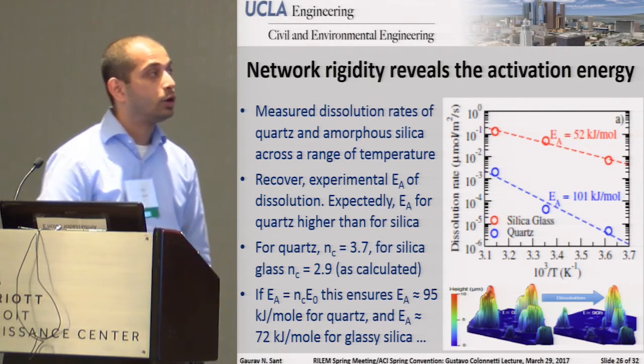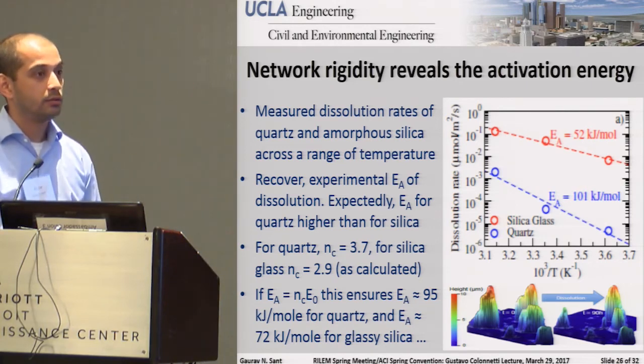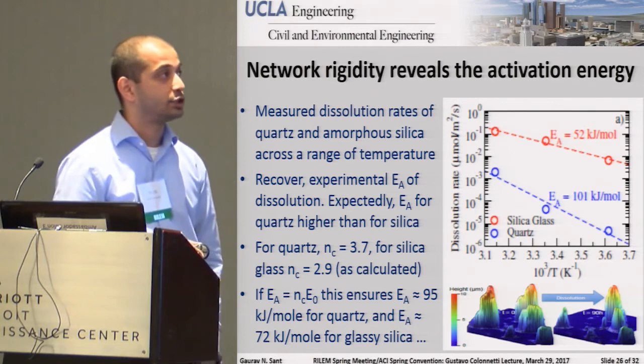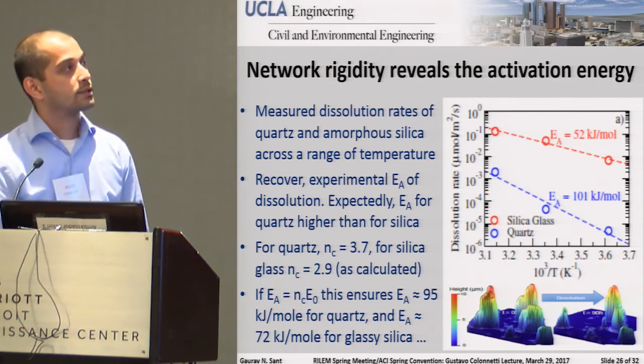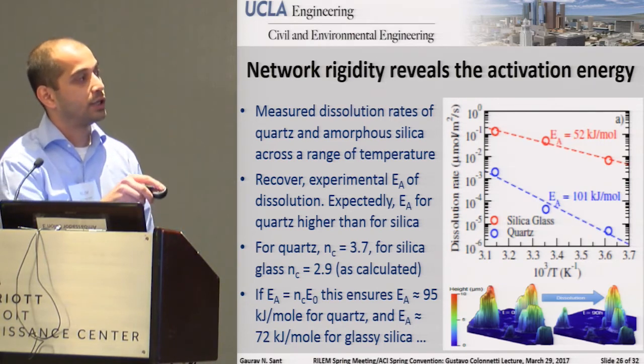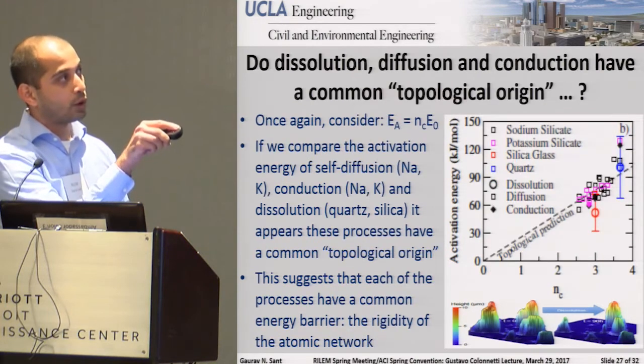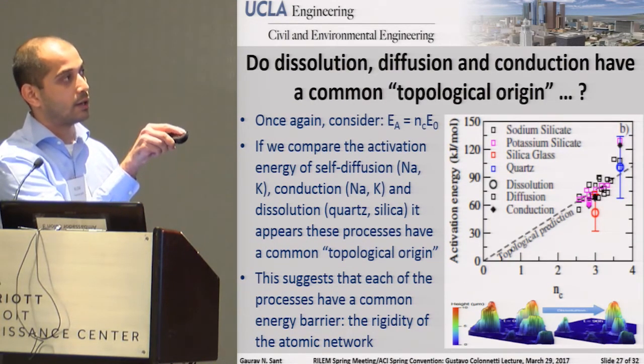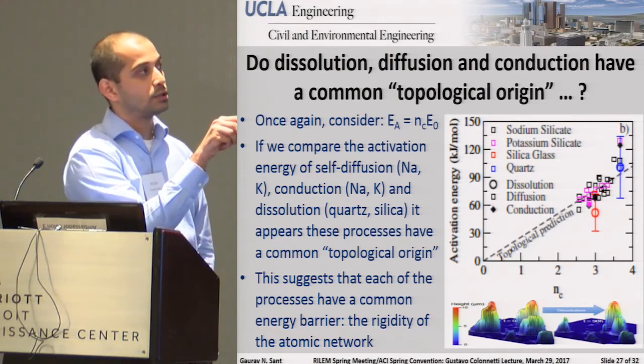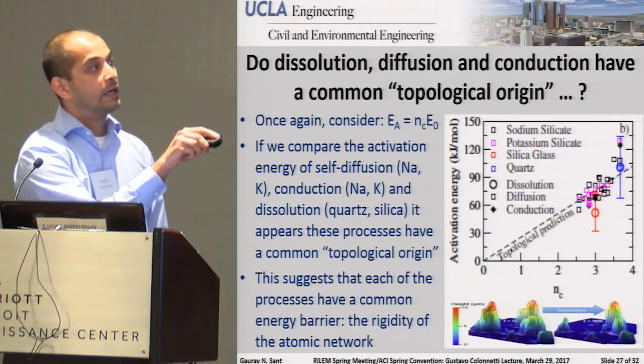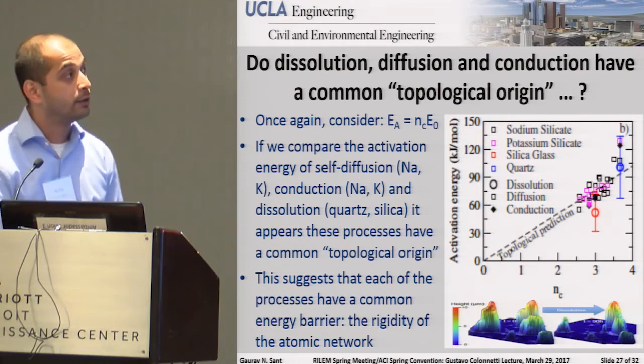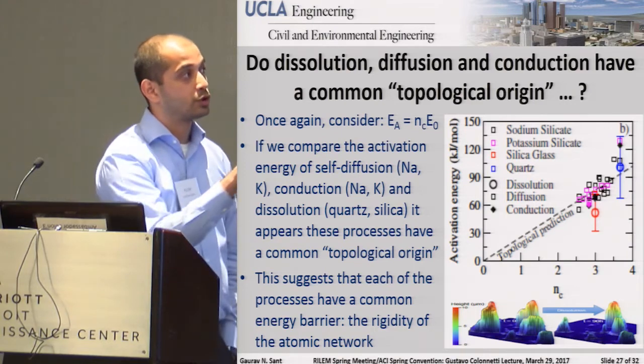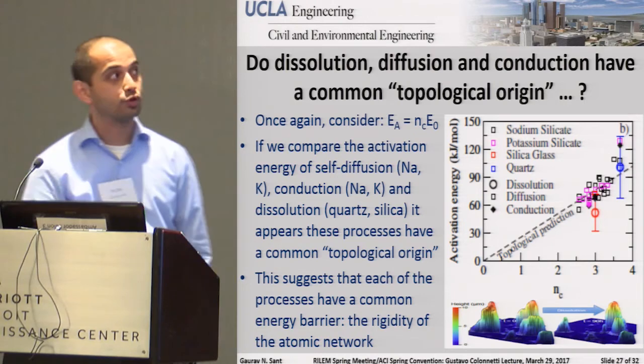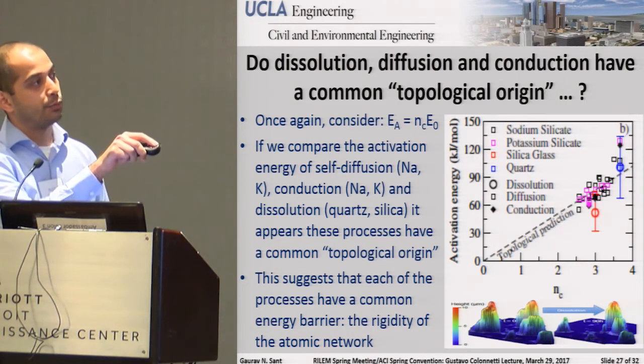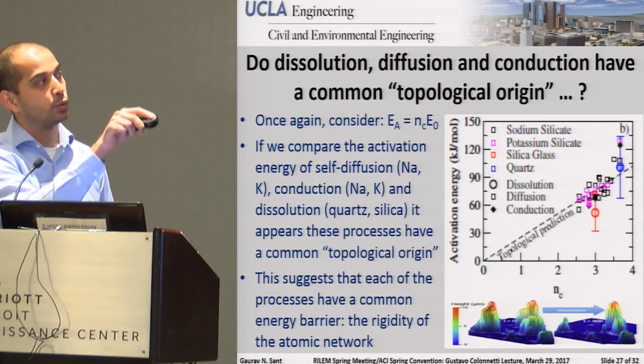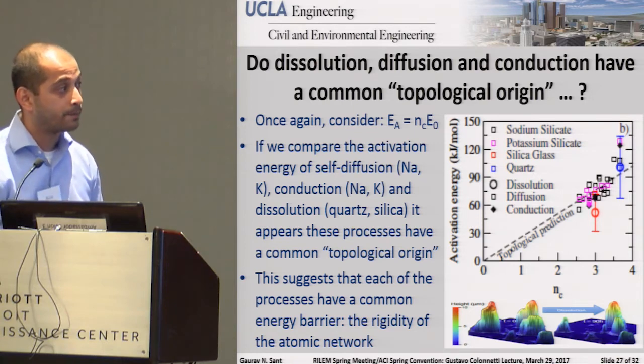Now, this is actually really quite good because what this tells you is that you are able to get an indication of the activation energy. When you start to look at this in a broader context and you look at activation energy as a function of number of constraints, for four different solids, sodium silicate, potassium silicate, silica glass, quartz, where you're looking at processes including dissolution, which is underwater, diffusion, which is the movement of species at high temperature, and conduction, where it's ionic hopping at high temperature, you can start to tell that the topological prediction basically follows quite well with what the activation energies of all of these processes are.